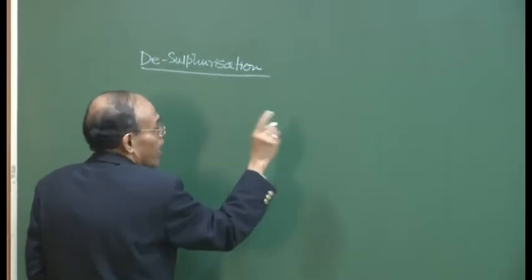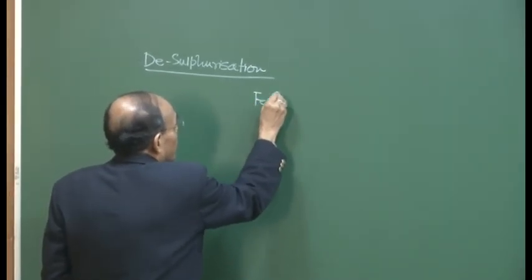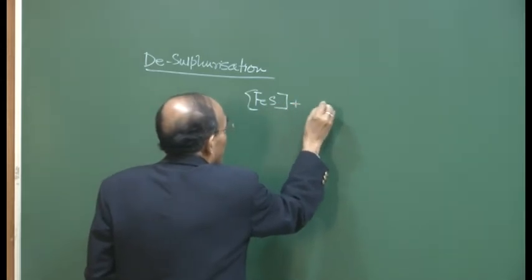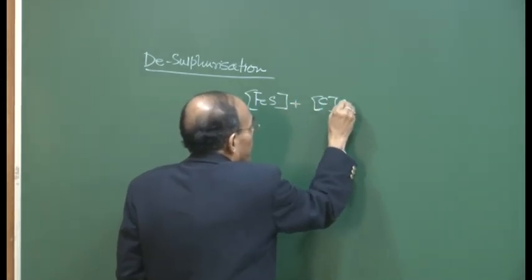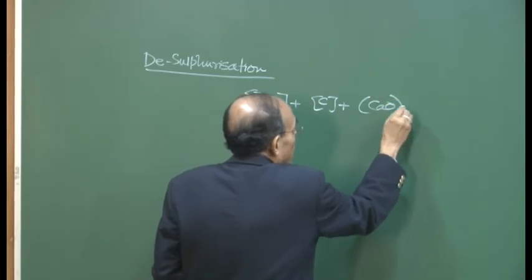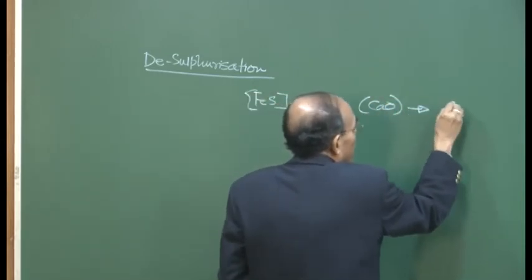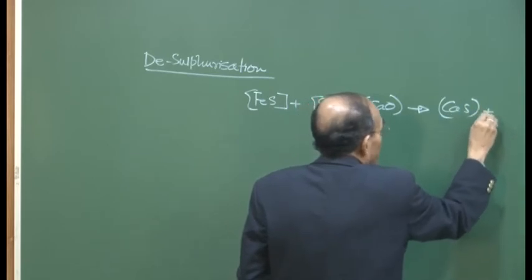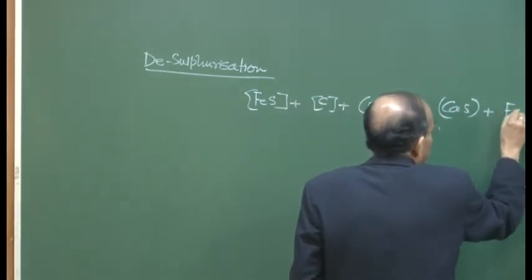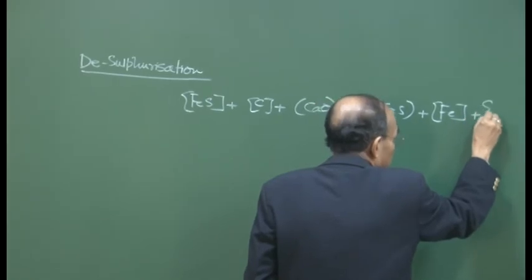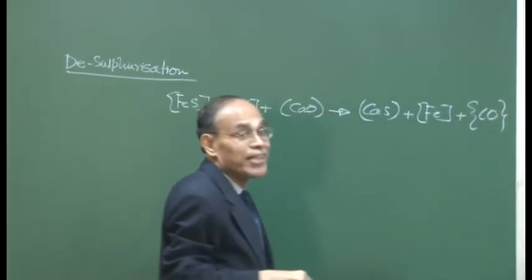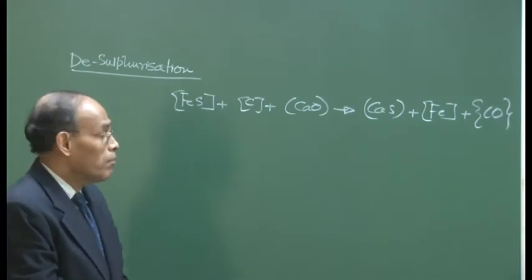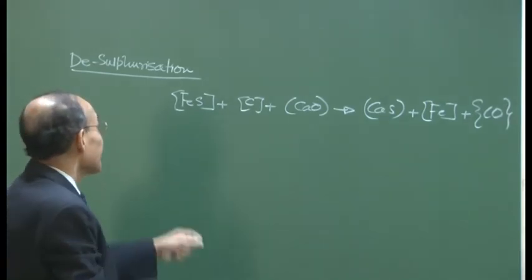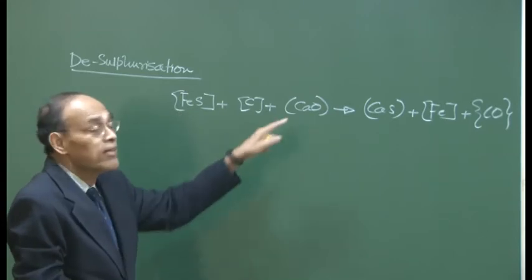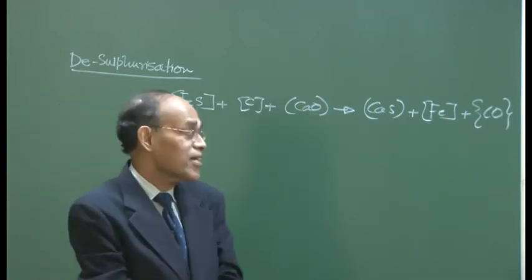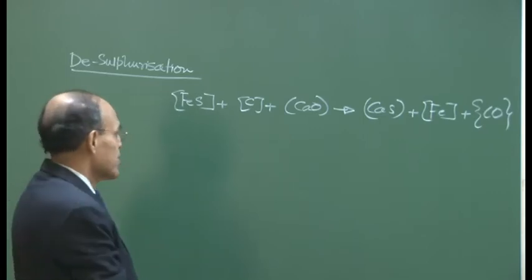Now, in a molecular form, I have written this equation: molten metal sulfur plus carbon, and then we get calcium sulfide and gases. Gases will be written with second bracket, parent phase or those elements which are dissolved in metal in third bracket, and the oxides, the slag forming reagents, in the first bracket. This is the molecular form of the desulfurization reaction.